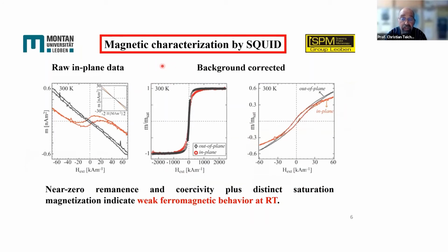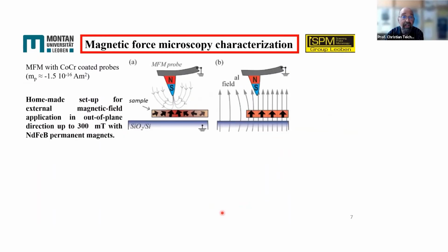Here is a summary of the magnetic characterization by SQUID, and the black line is a non-iron or very little iron containing reference sample, also from an area nearby in Leoben. But we see a clear, in the raw data, a clear but small hysteresis. That is here in-plane data. We see it also out of plane at room temperature. So we see an indication of weak ferromagnetic behavior at room temperature.